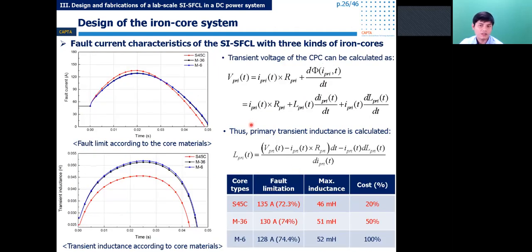The fault limiting characteristics of the SFCL with different core materials were analyzed and compared by using the FEM simulation. In theory, the SFCL limits the fault based on the transient inductance of the primary coil, so we can calculate this value based on the transient voltage and transient current. As a result, you can see here, the fault limit of the SFCL with different core types were not significantly different. The limitation rate was higher than 70%. But considering the material cost, we selected the S45C core and the M36 core to manufacture, test, and compare in the experiment.